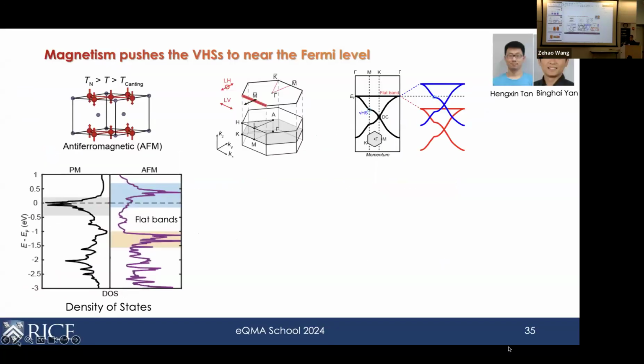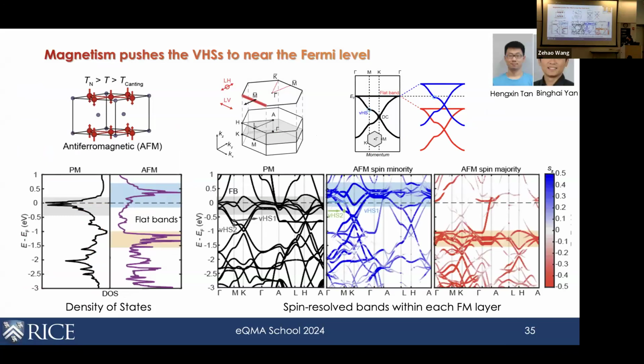Another way to ask it is: will this happen on all A-type antiferromagnets? Here, largely because the in-plane Kagome layers are preserved, we can think about what happens within each layer, and within that layer it is ferromagnetic. So if you calculate the spin majority states, spin down could be the majority and spin up the minority. But if you go to the other layer, it gets swapped. Within each layer, at least from DFT, this picture is correct: projecting the spin minority and spin majority states, it looks like a spin splitting. But the flavor of spin up versus spin down would change. Overall, if you do spin-polarized ARPES on this, you would not see spin polarization on the bands.